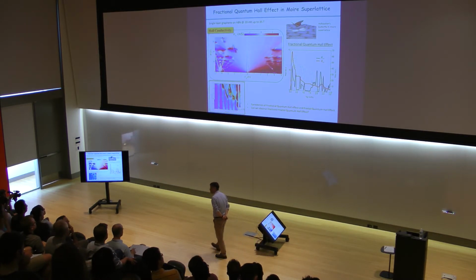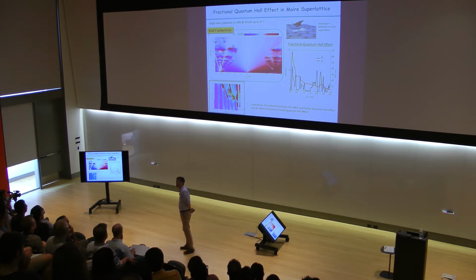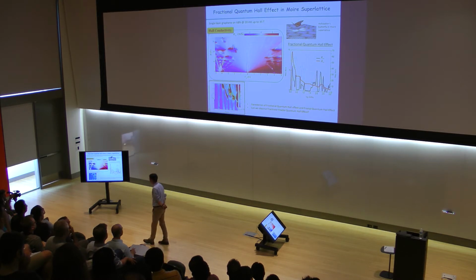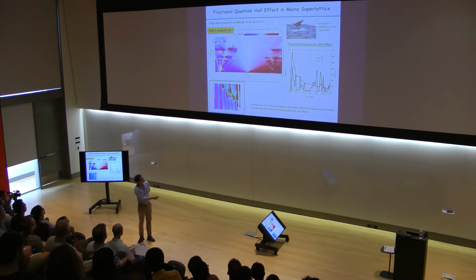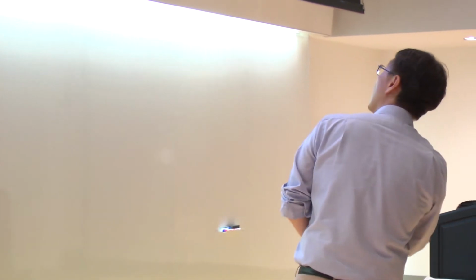This is a good example: once you apply a strong magnetic field, you start to see that your transport shows this quantizing effect, what you often call the quantum Hall effect. But it's not only the quantum Hall effect. It turns out there's an interesting interaction between the graphene and boron nitride, where what you call the Moire pattern forms and gives us the superlattice, which actually quantizes the graphene band even further and creates all these complicated structures. I'm not going to discuss anything in detail here because it's a little bit of an esoteric subject.